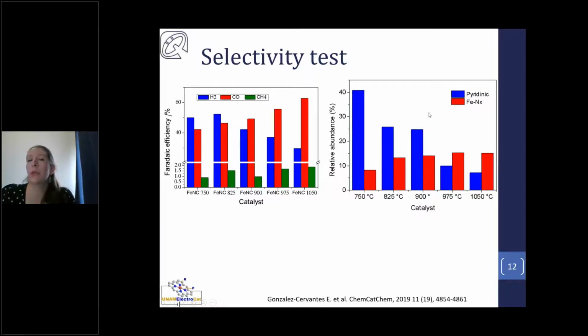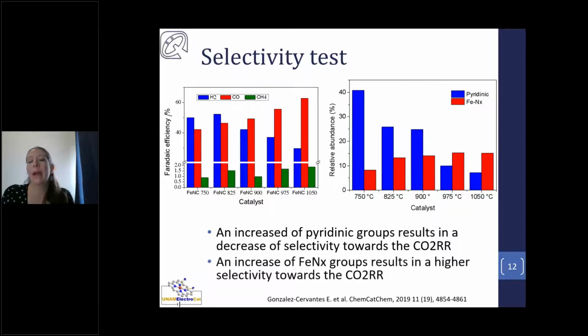I'm pointing these two sites because, as I will talk to you later, these have been proposed as the active sites in this carbon-based material. So it would seem that by having a higher synthesis temperature, we are having a greater number of iron coordinated to nitrogen, which has a positive effect on the selectivity of the process. This is a strong indication that the iron sites are the predominant catalytic sites in these carbon materials. To confirm this,